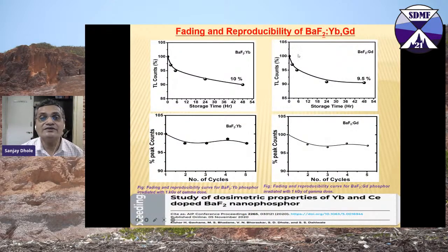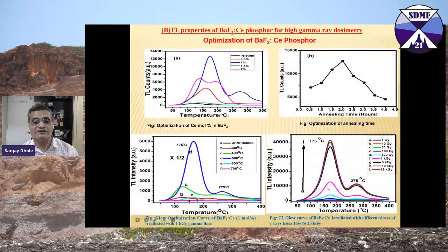So this is fading and reproducibility. This is a fantastic study which has been carried out for barium fluoride. Here the fading is 10%, and reproducibility was checked for 5 cycles. We have done it for 5 cycles, and it is quite good. For barium fluoride doped with gadolinium, the fading is 9.5%, and again you can have very good reproducibility.